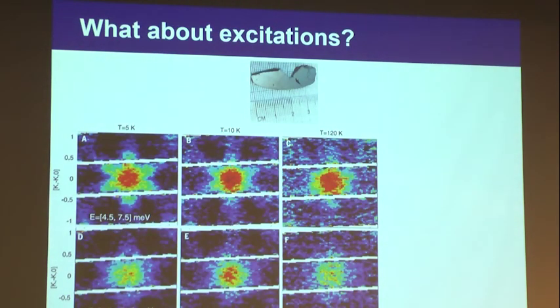Last but not least, I've been talking a lot about ways to suppress magnetic order. I've been obsessed with magnetic order suppression. But the other experimental knob or tool that I told you would be a guide in this adventure is magnetic excitation. It turns out that probing magnetic excitation in this Kitaev type of material is very difficult because, first of all, a lot of them are iridates, and iridates are notoriously difficult to study with neutron scattering. Of course, there are great instruments that we can use here at sector 27, but the energy resolution is not there yet. I know that there is a high resolution effort going on in sector 27, but it's still not there to address the spin-wave excitation spectrum in iridates.